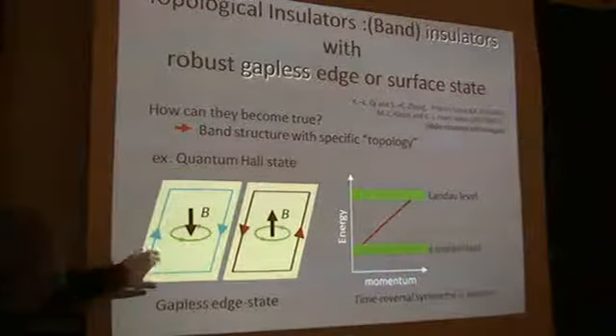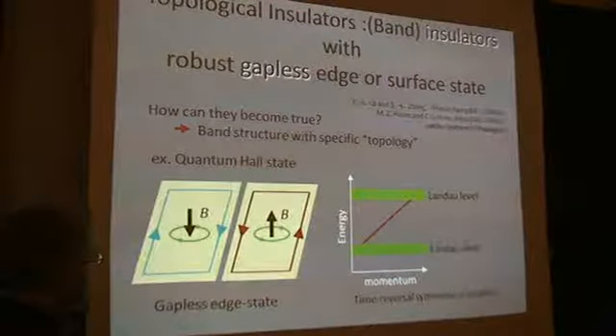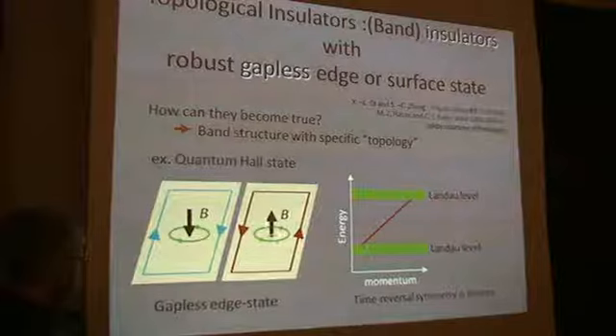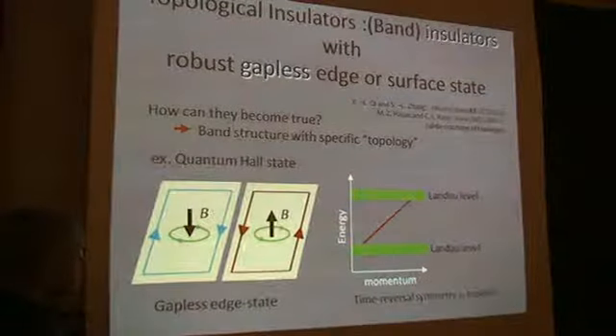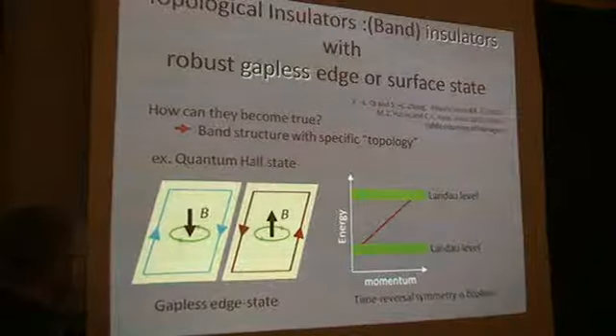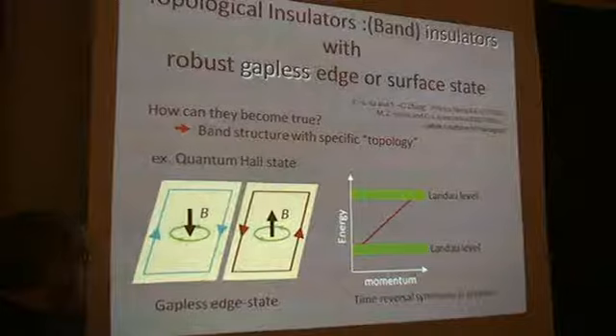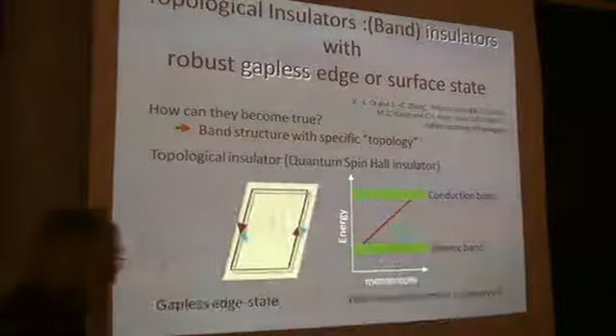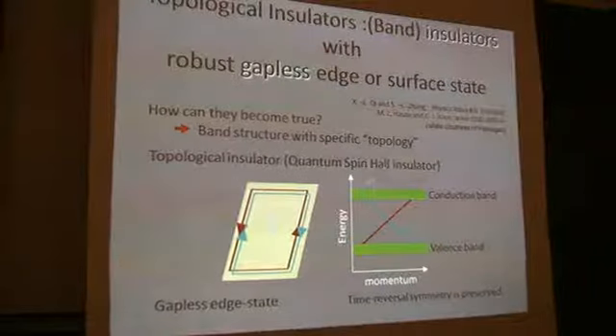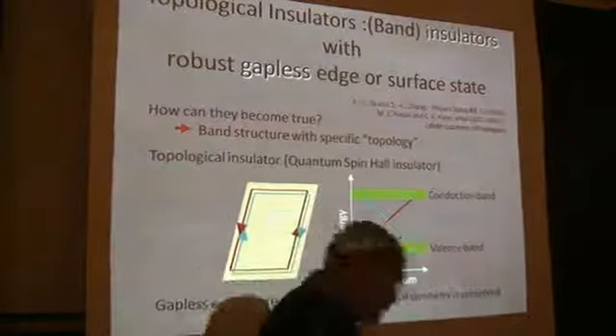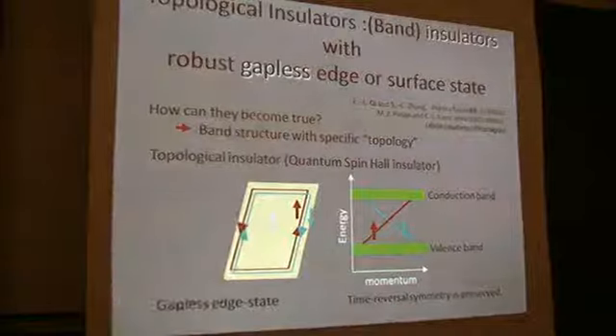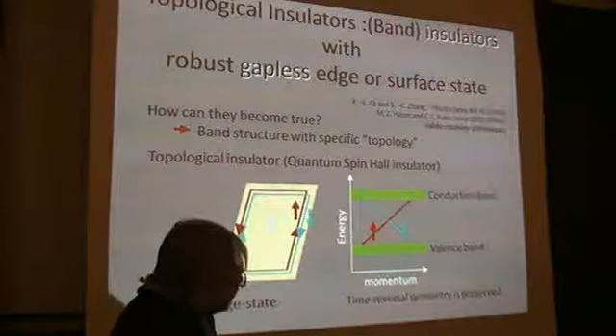So the way to arrange a time-reversal invariant non-trivial insulator state is to suppose I have a spin-orbit coupling that is clever enough to force my effective field to point up, for instance, for spin to the left and point down for spin to the right. Namely, if I have two spin species, they see opposite values of magnetic field. They both do the chiral motion, but in opposite directions. Then the net magnetic field applied to the sample is zero, and I have two counter-propagating edges. But because of the strong spin-orbit coupling, my scattering from one side of the branch to another is exactly forbidden. So the backscattering is forbidden. But this is all true, like I said, for the one-dimensional case. And in the two-dimensional case, one needs to solve the multiple scattering problem. You cannot argue presence or absence of the in-gap states based on the Born scattering argument.